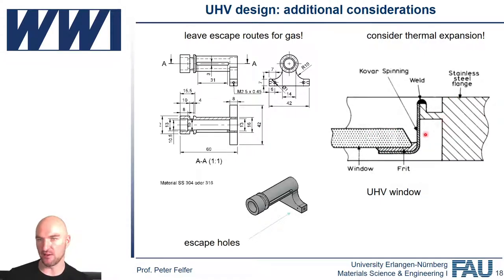And so you usually have some Kovar or some other material. Kovar is called Kovar because it has the same expansion coefficient as the glass, so that the thermal expansion can be equilibrated through some means. And this is something you always need to take care of, because otherwise your viewports would all break during baking. And that's something we obviously do not want.